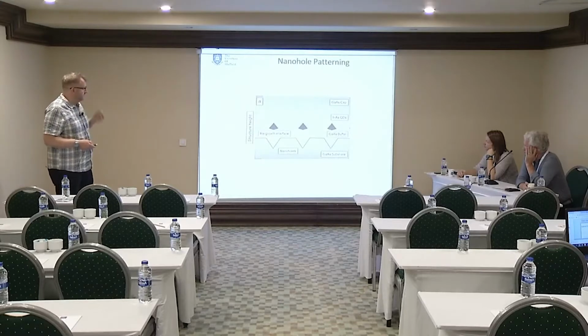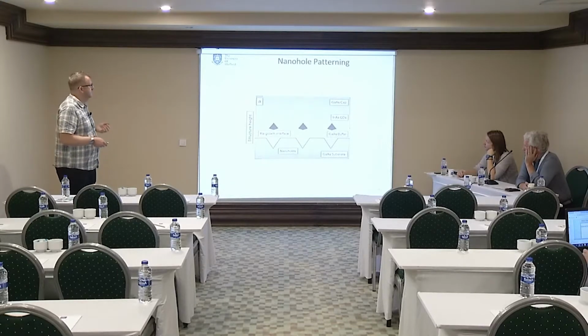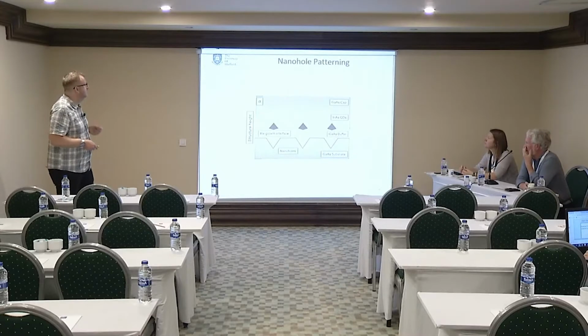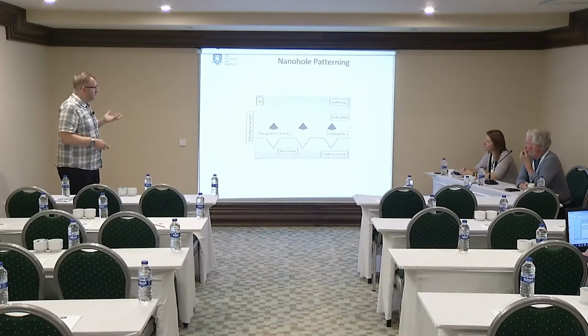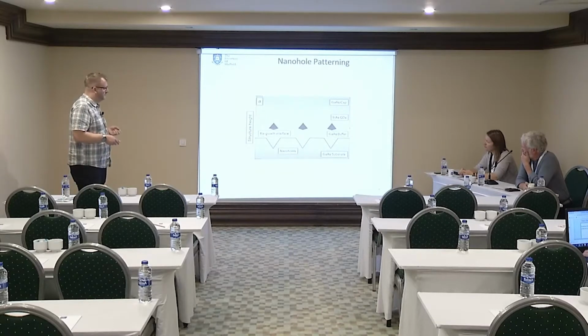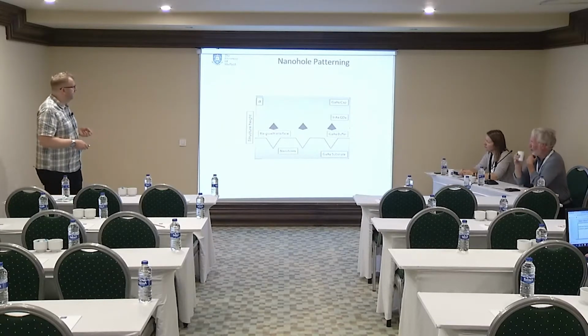So the approach that we're going to use seems quite simple. We're going to grow part of our wafer and then take it out and etch the surface. So we etch the surface to create some kind of nanohole. It's not necessarily triangular. This is a cartoon. Create our array of pits, put it back into the growth system, grow a bit more gallium arsenide to smooth the surface out, and then hopefully the indium arsenide will nucleate preferentially at this step because we've modified the chemical energy at that point. And then we finish off the structure and encapsulate it.